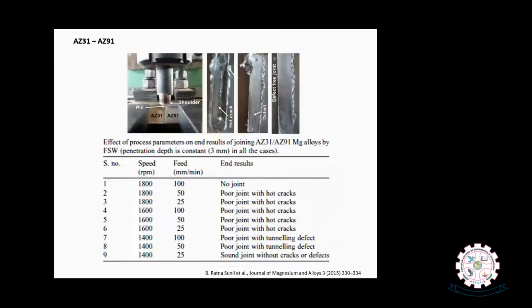And these are the studies of joining dissimilar magnesium alloys within the magnesium system, AZ31 and AZ91 magnesium alloys. You can see the photographs of the joints and the defects, and the combination of process parameters that we have adopted. In most of the cases we end up with a poor joint because of hot cracks and the tunneling defect. Whereas at 1400 RPM and 25 mm per minute, we have achieved a sound joint without any cracks, tunneling defects, or other defects.